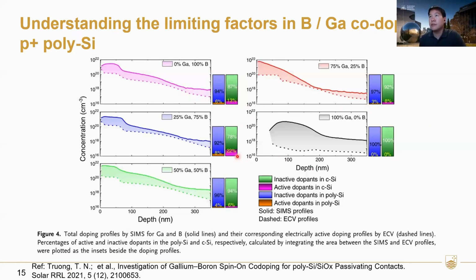If we just focus on this image on the bottom right-hand side, this is a comparison of the SIMS in the solid line, and the dashed lines are the ECV, the electrically active dopant of gallium doping. We see that with gallium doping, we get really good passivation, but we can't get good contact. That's normally understood as because the solubility limit of gallium is not as high, so it doesn't provide the level of concentration needed to form good electrical contact.